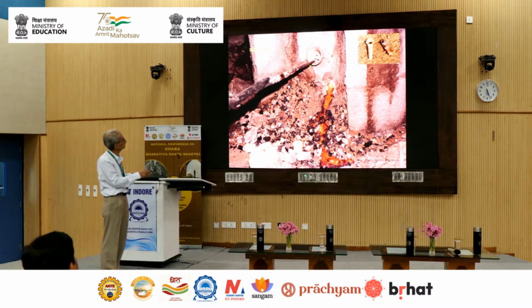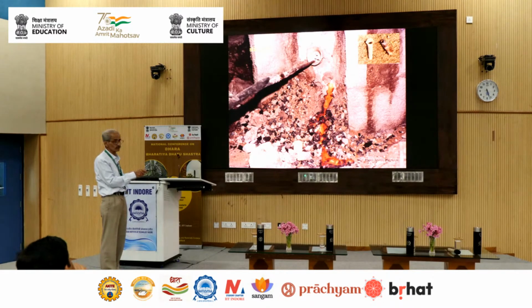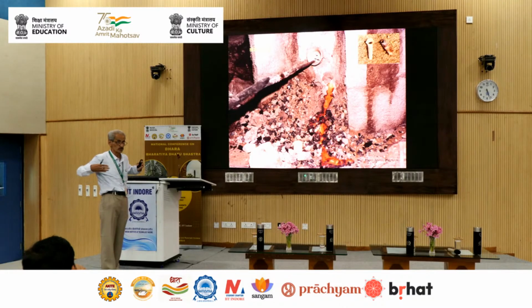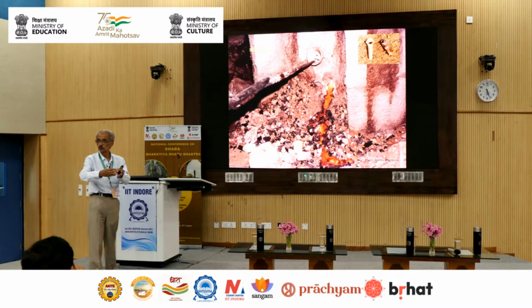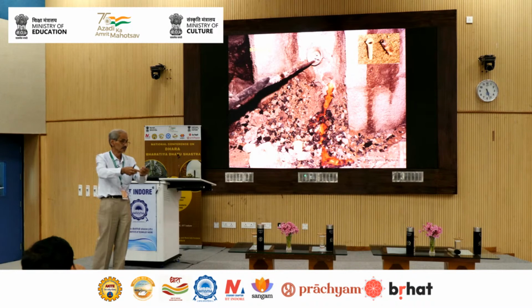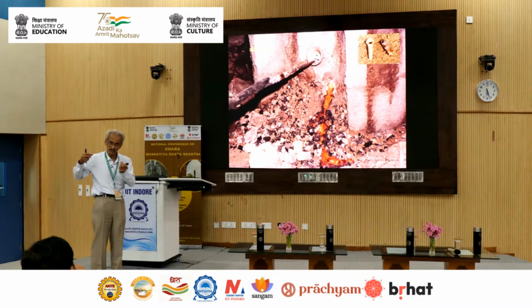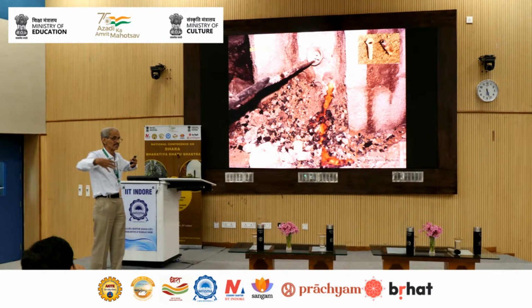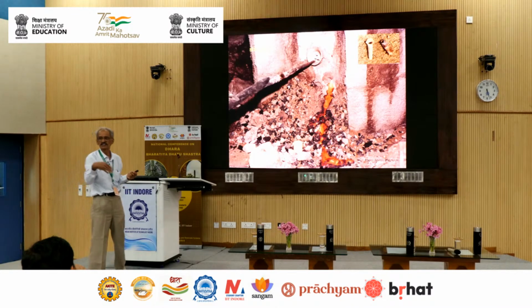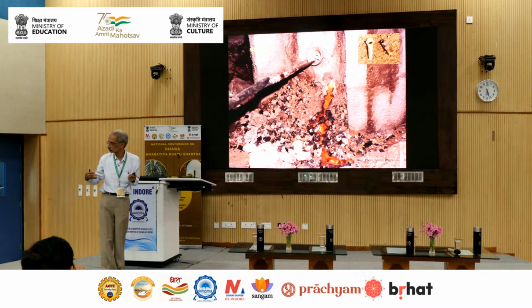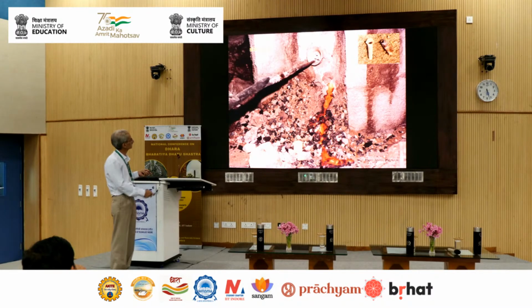The tuyere is like this, please. This is, of course, a photograph from IIT Bombay. The tuyere is of the aspiration type. Then the blowpipes from the bellows don't come and join, seal. They are just kept in front. So it is like the aspiration tuyere. So when the jet of air goes, it also brings in atmospheric air. So if you blow 100 liters per minute or so, you'll probably take in another 50 to 75 liters of air from outside. That's how.